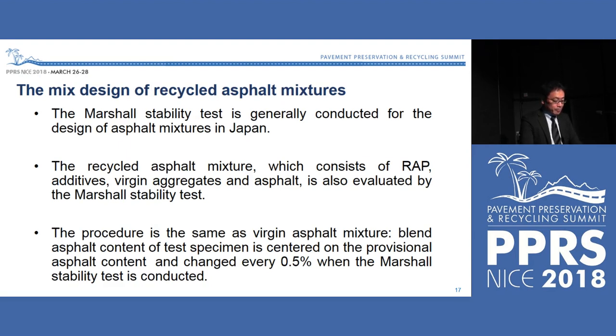I'm going to explain the mix design method of recycled asphalt mixtures. The Marshall stability test is generally conducted for the design of asphalt mixture in Japan. The recycled asphalt mixture, which consists of RAP, additives, virgin aggregates, and asphalt, is also evaluated by the Marshall stability test. The procedure is the same as virgin asphalt mixture. Blend asphalt content of test specimens is centered on the provisional asphalt content and changed every 0.5% when the Marshall stability test is conducted.